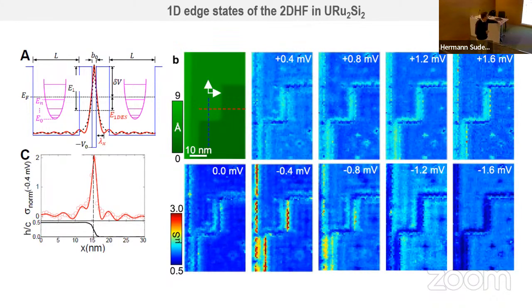So this can be modeled through a quantum well, and then you see that there is a high electronic density of states whenever you are in this localized state. So here you see there is a high conductance in this energy range, because here there is a one-dimensional edge.